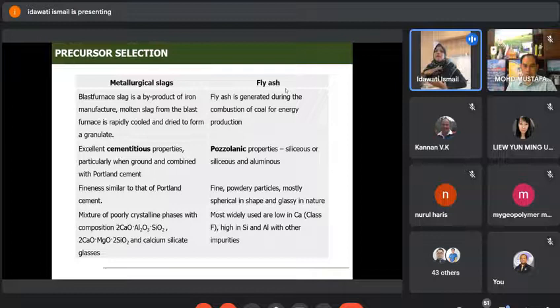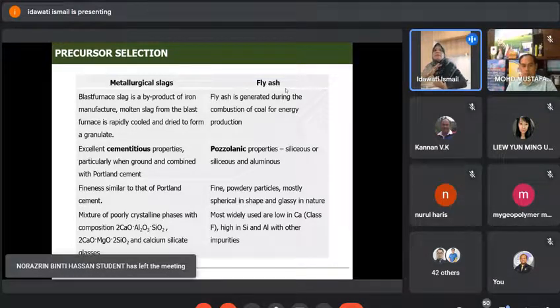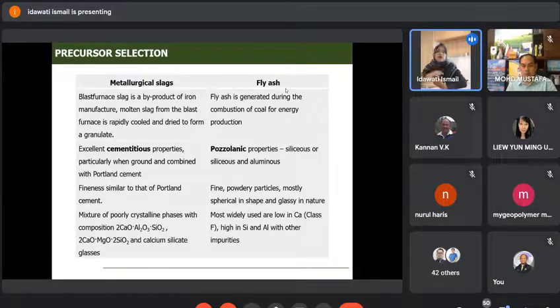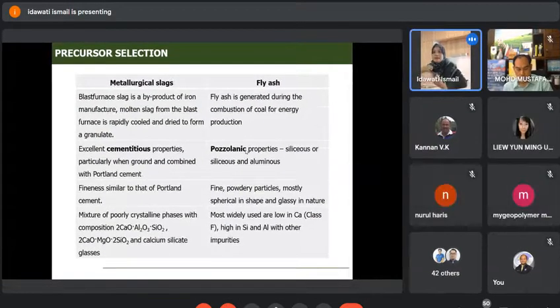And this fly ash, there are two types: one with high silicate content and low calcium content, or high calcium content. In Sarawak, what we found is that our fly ash is low in calcium. In general, fly ash has good pozzolanic properties, which means it's high in silica and very siliceous, giving you siliceous and aluminous products. This property is good. If you mix it with cement, it can liberate some of the silicate and aluminate to give you secondary products, and can also help with workability, giving you a more compact structure. It is very fine, powdery particles, mostly spherical in shape and glassy in nature.